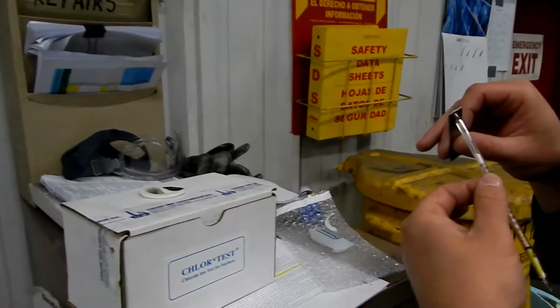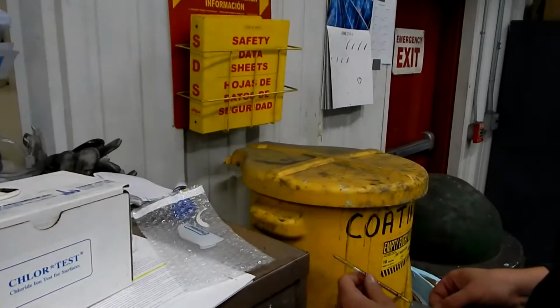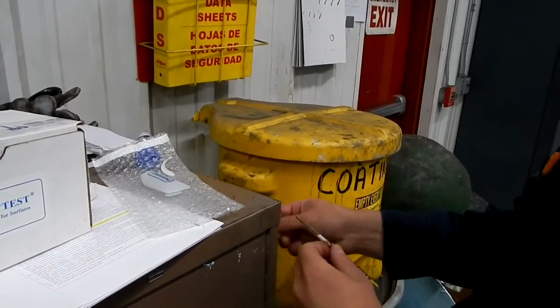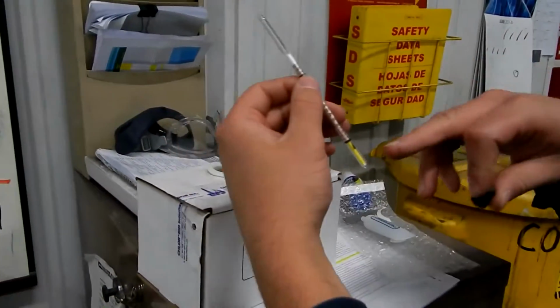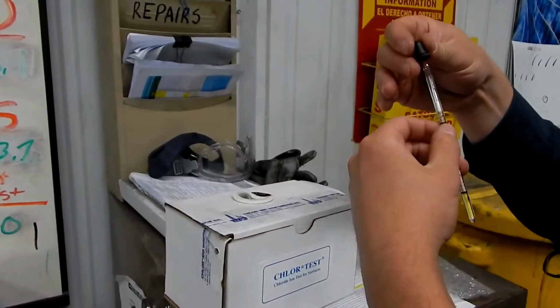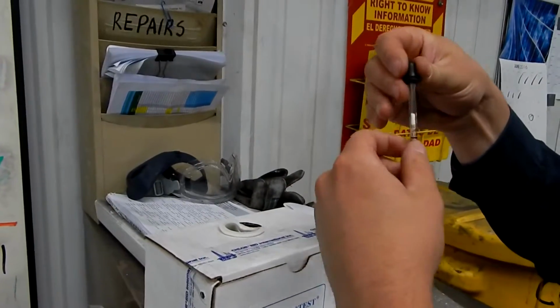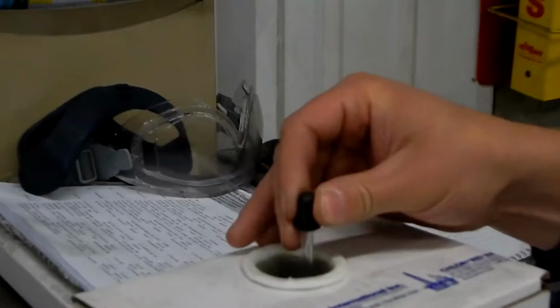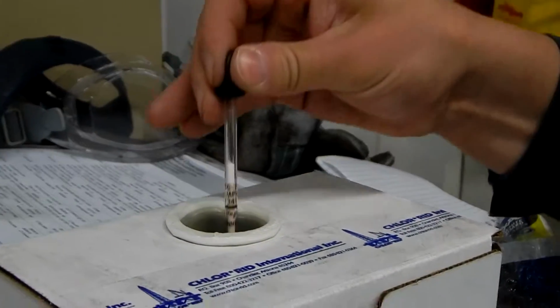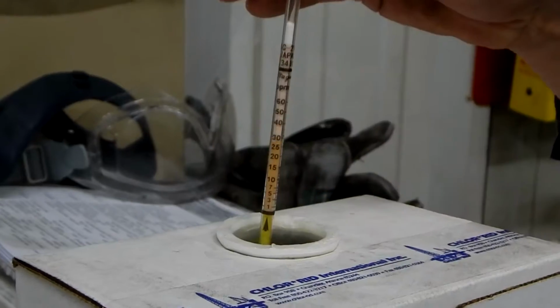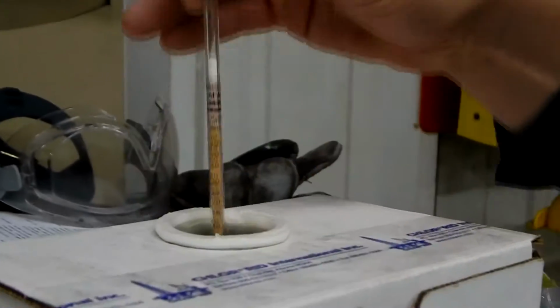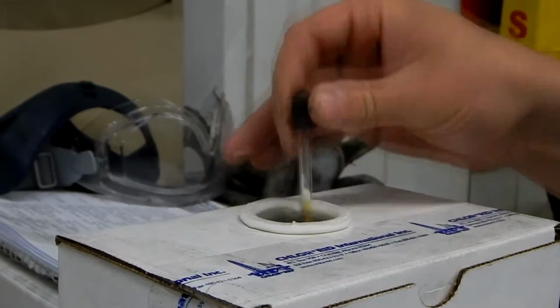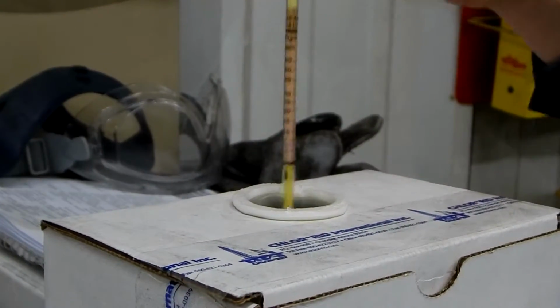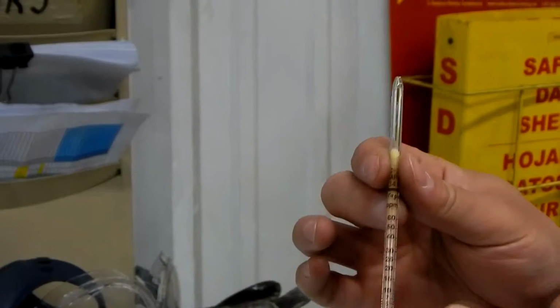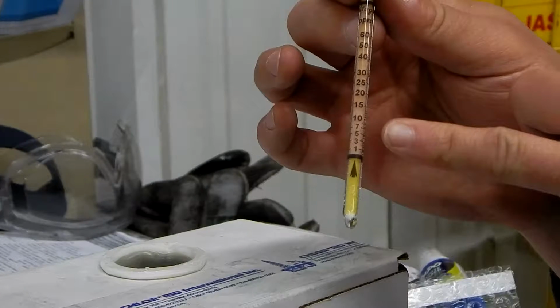Carefully break the ends off of the glass tube by sticking the tip in the hole in the metal piece and pulling carefully. Apply the rubber stopper to the end opposite of the yellow part. Begin to fill the glass tube with water by placing the yellow end into the water, applying pressure to and then releasing the rubber stopper. Once the tube is full, check for discoloration. White and pink discoloration may not reach above 5 ppm. You may then record your results in the daily QC log.